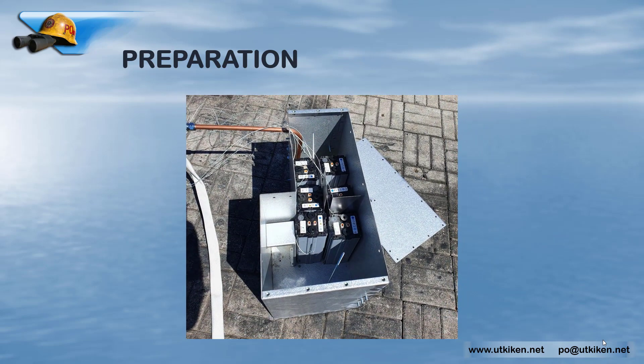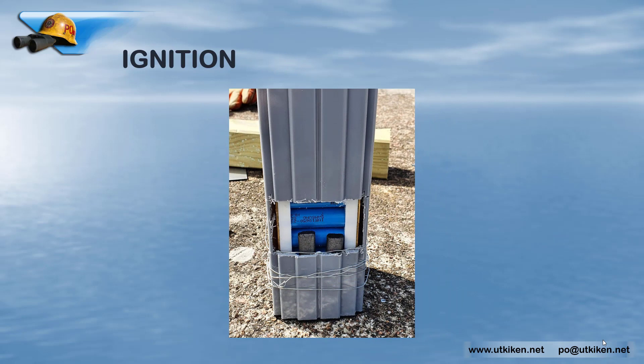Here you can see the modules within the battery box with about a 6 to 12 millimeter spacing — a quarter to a half inch. Lithium-ion batteries are not easy to ignite. It takes quite an effort, even when heating them directly with smoldering carbon rods like I did here. I even had to help it out a little bit extra with a propane torch to get it started.